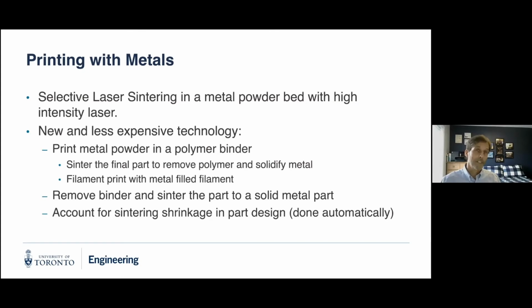But there are some less expensive and newer technologies more recently. There are a couple of ways of printing that powder and just binding it. We could have a powder bed with some polymer coating on the metal particles, and we could hit those with a lower power, low temperature laser beam to glue the metal together. Or we could filament print with a metal powder filled filament. In that way, we could make a part that is metal particles bound together with polymer. And then we remove the binder and sinter the part into a solid metal part.